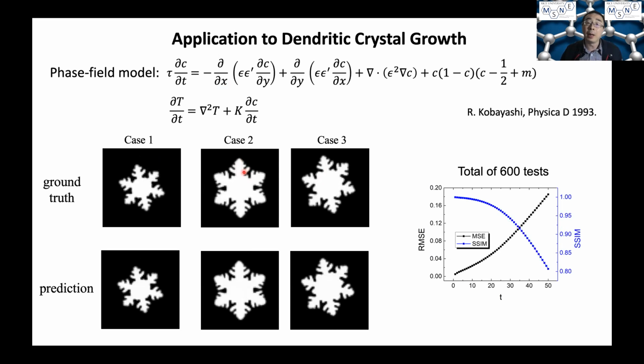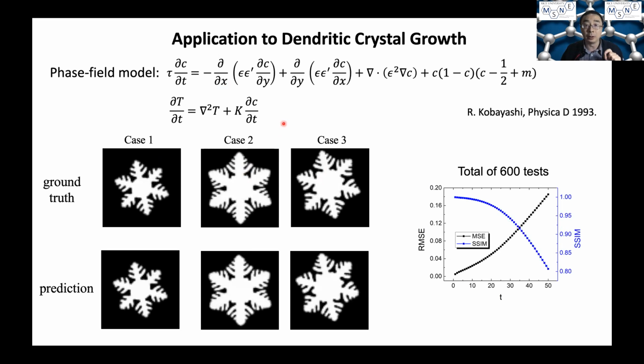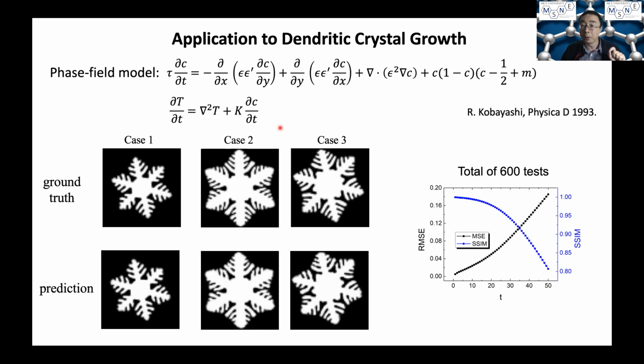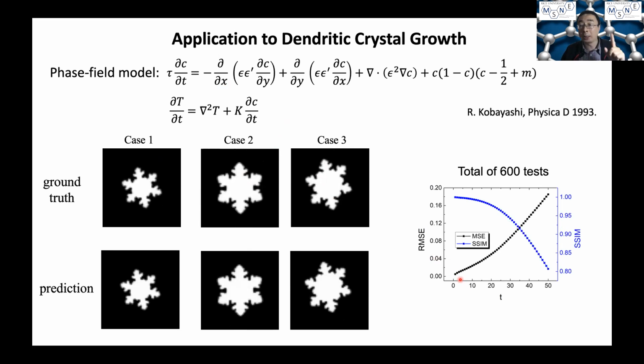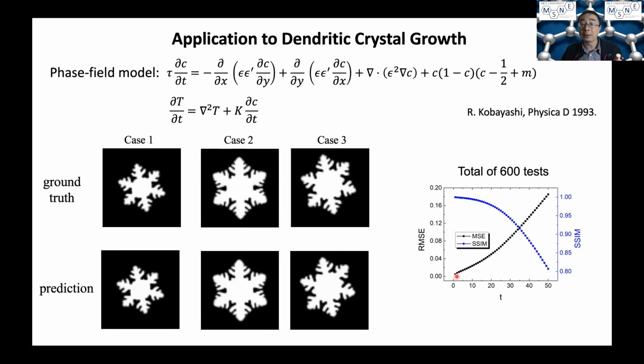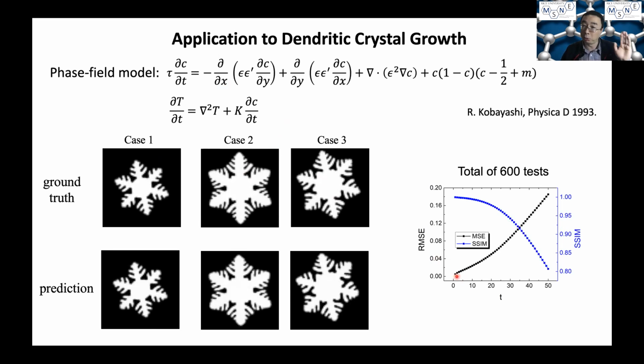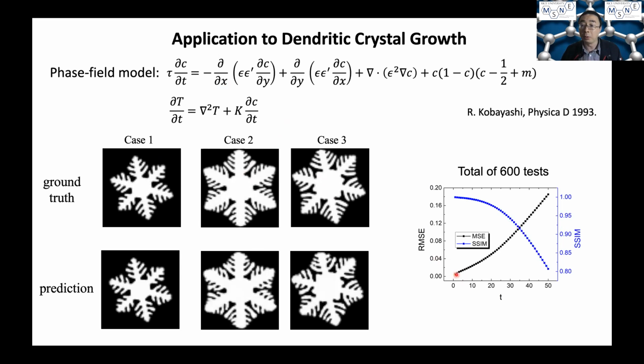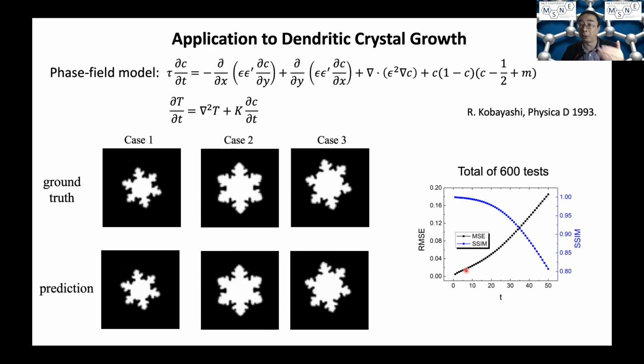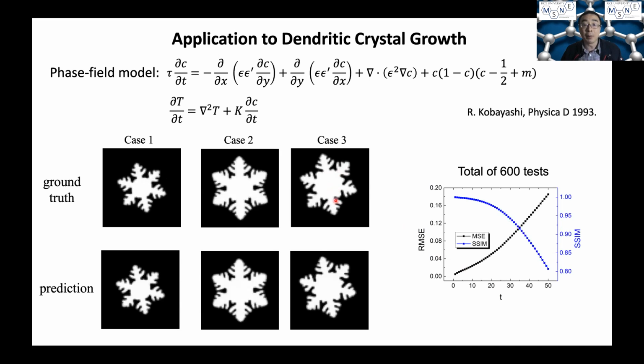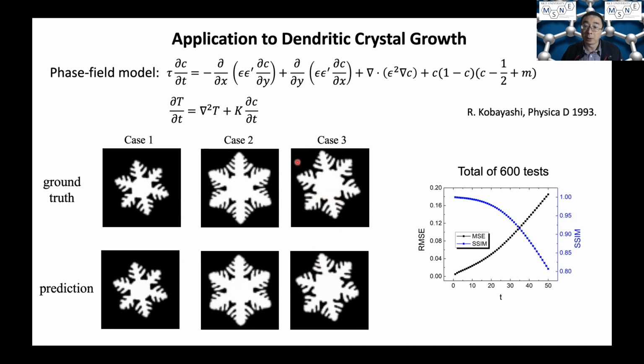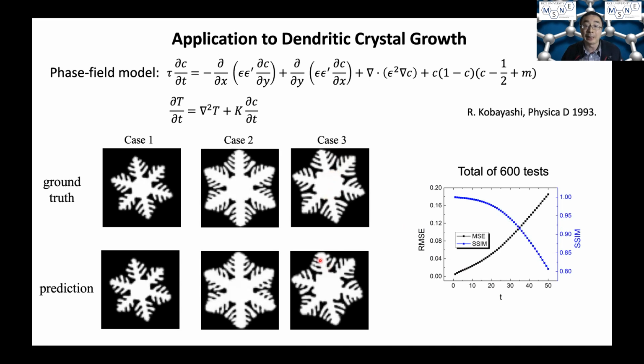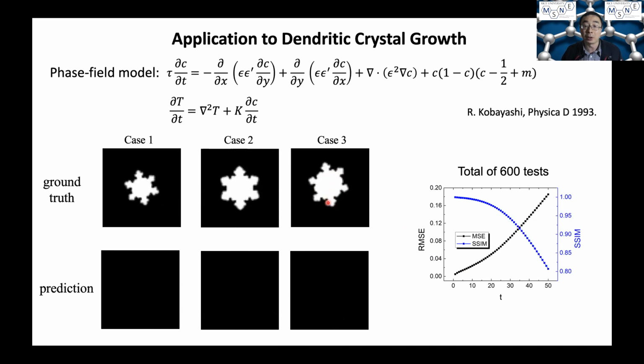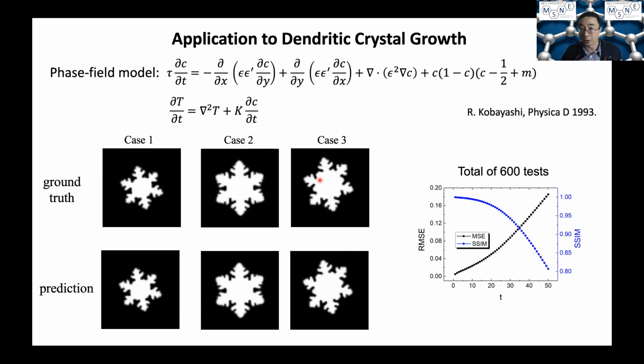What we found out is because the process is more convoluted, it does pose challenges for the RNN to make a good prediction. So for example, instead of giving only one input frame, we found we need to provide the model with 10 input frames to show a short sequence of evolution to allow the model to learn the evolution trajectory and make good predictions on the dendrite growth pattern. But the model is indeed able to capture pretty well the whole process of dendrite growth and even capture the details of the formation of the side branches and when it forms very nicely.